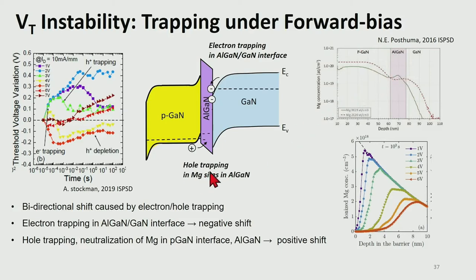But under positive gate voltage stress, the polarization field in the AlGaN barrier is reduced, and a lot of holes can be injected into the AlGaN barrier. And this effect reduced the number of ionized magnesium concentration in the AlGaN barrier, as you can see in this figure, and this can cause a positive VT shift.